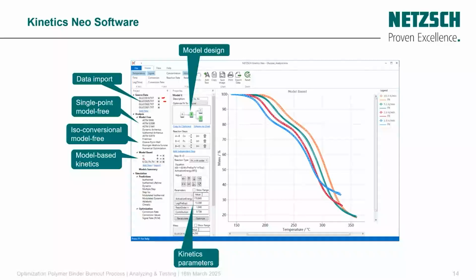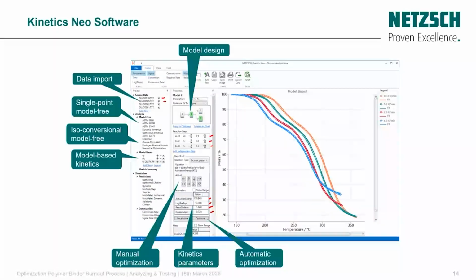Here also we can determine or get all the different kinetics parameters. For example, in this case, we have the model-based and we have 3 reaction types. And here we have the step B goes to D, and these are all the kinetics parameters of it: the activation energy, the log pre-exponential factor, the reaction order, and the contribution. Also, we have the option of manual optimization and also automatic optimization.